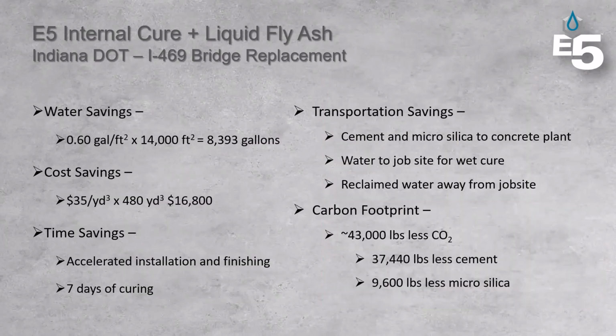So what did we accomplish? Well, when you remove wet cure, 7-day wet cure, you save about 0.6 gallons of water per square foot. That's 8,300 gallons of water. That's enough for 100 people for a day. We saved $16,000 because it was $35 cheaper per yard. And we saved time, 7 days less of cure time, accelerated installation and finishing.